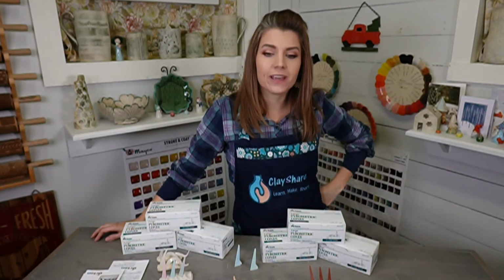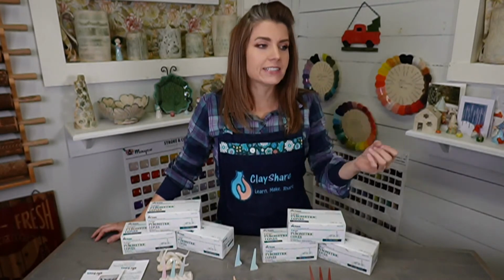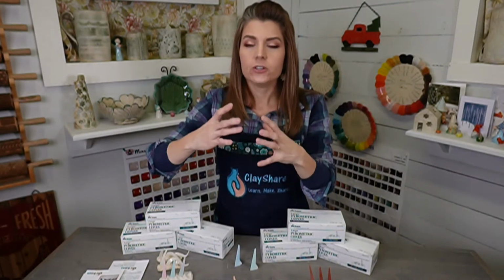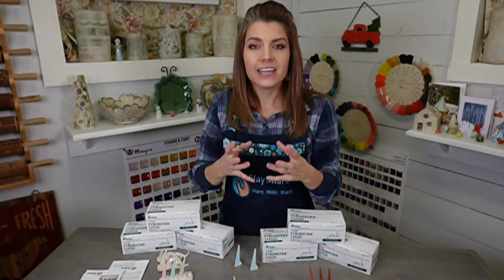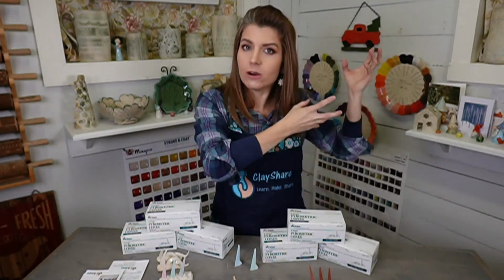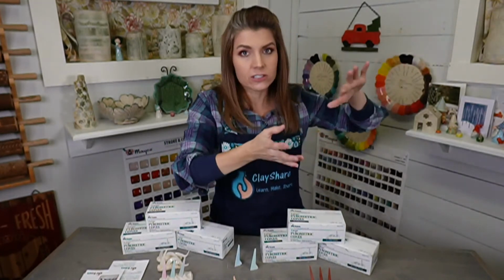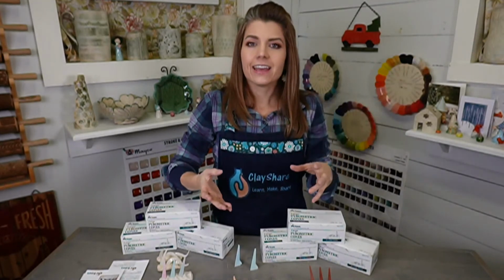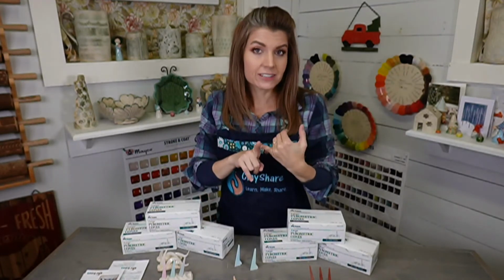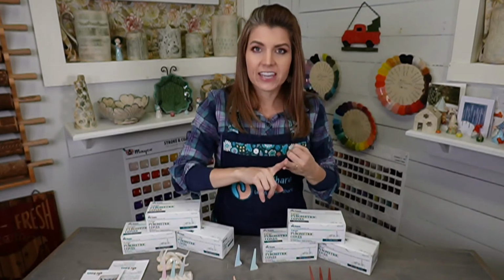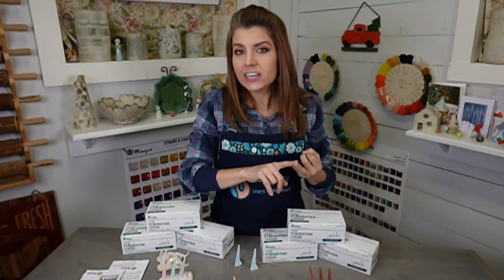You got it. So you just bought a vent kit. You hope it helps your glaze effect. Tanya, I think it will. What happens is when we fire with vents, it circulates the air more. You get a more even firing happening in the kiln. You get a cleaner firing too, because it's pulling everything out that's burning off, and it's pulling it out into the environment. It's okay. It's going out there. And you're not breathing it. You're not breathing it, so that's good for you. You're pulling everything out of the kiln, so the atmosphere is cleaner, and you're moving that air around so you get a more even firing.